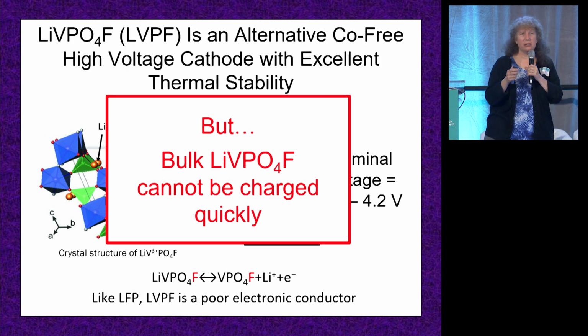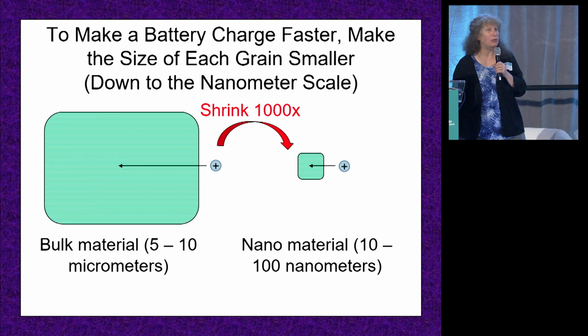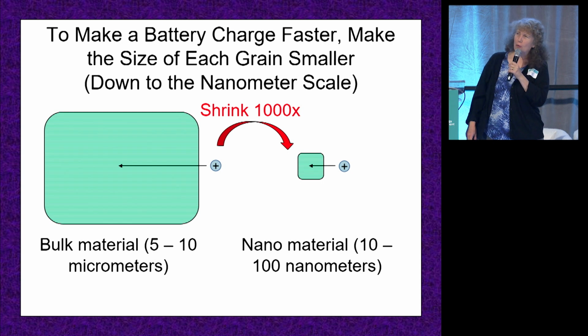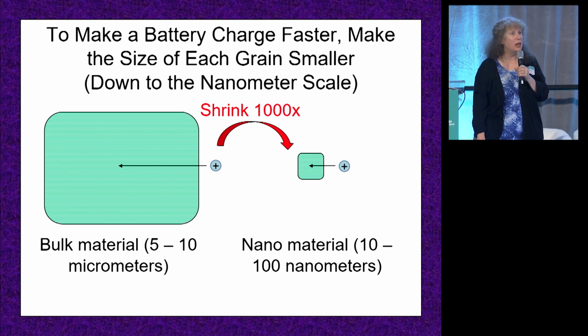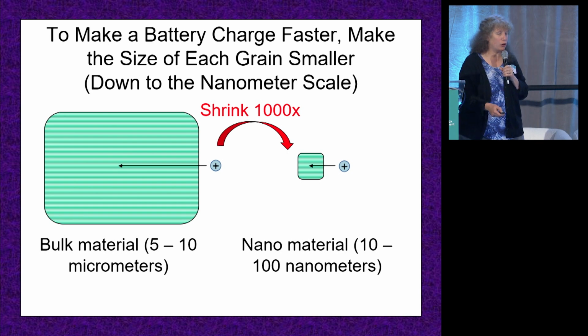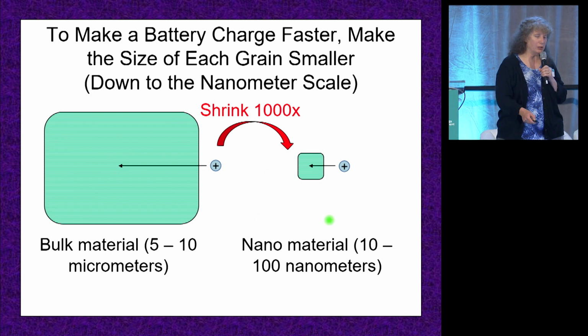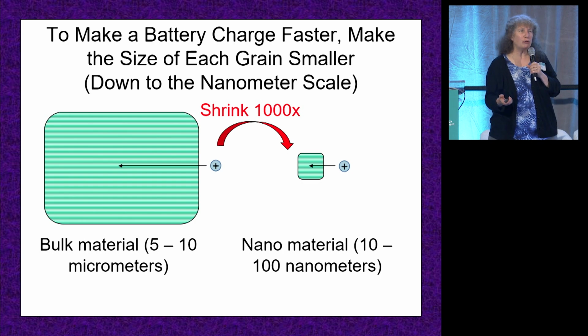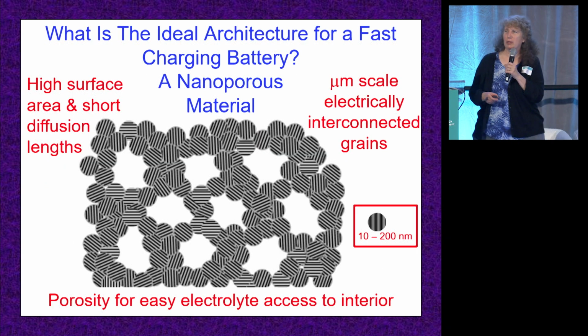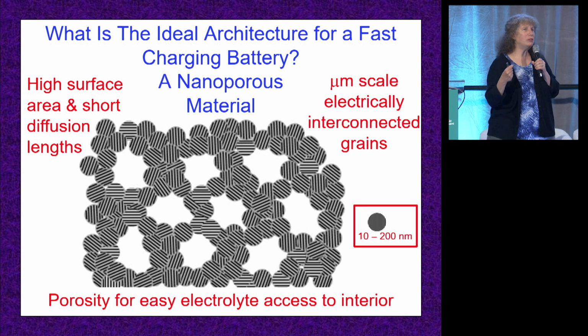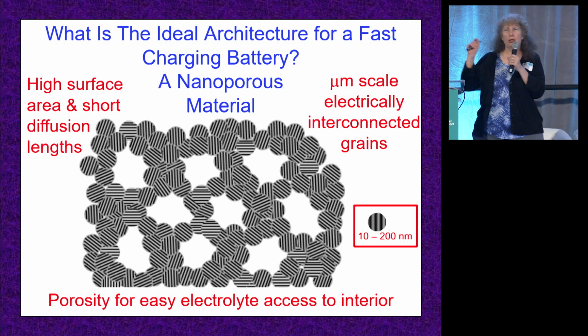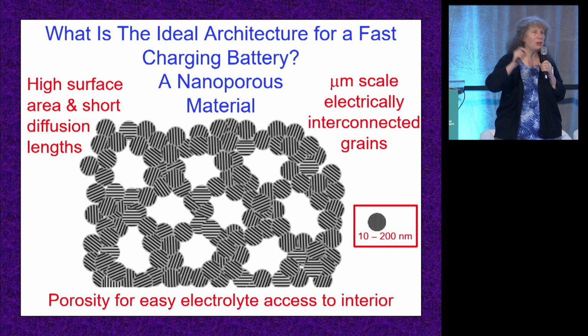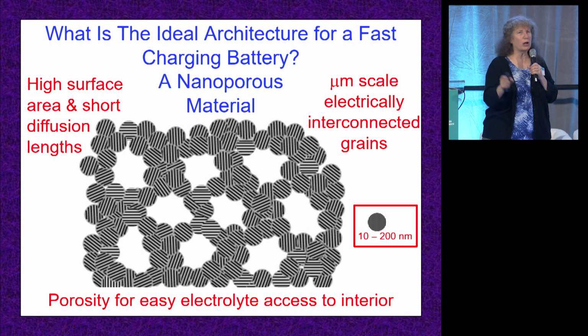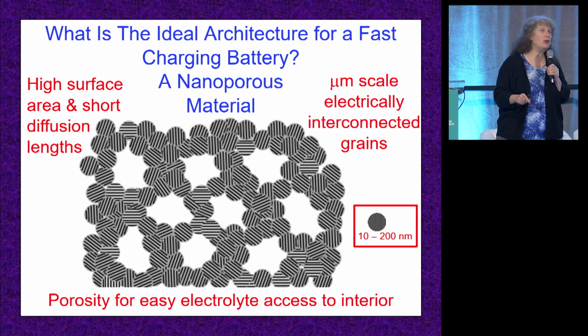So how do we make this a fast charging material? Well, Bruce and I have spent the last two decades turning slow battery materials into fast battery materials. And we know how to do this. So the first thing is you have to go from big chunks of material to little tiny chunks of material. Unfortunately, that's not enough because if you make little tiny chunks of material, you can't get electricity through them. And so instead of just making little tiny chunks, what we make is a nanoporous network of that material so that the intrinsic size is small. Lithium ions don't have to move very far, but the whole network is electrically interconnected, and you have these holes for all the liquid electrolyte to flow through.